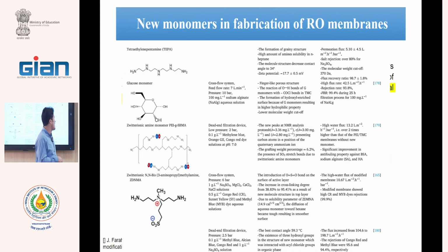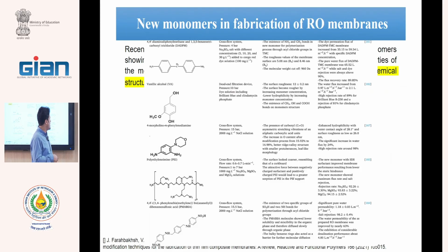Also, cause to the increase the biofouling with microorganisms and bacteria. Many monomers there are in literature, use of the dendrimers. This is a dendrimer with many amine groups. Some groups react with TMC, and other groups increase the hydrophilicity, and the excess amine groups can be used for post-treatment. After fabrication of RO, we can add some brushes on the membrane surface for reducing of the fouling.